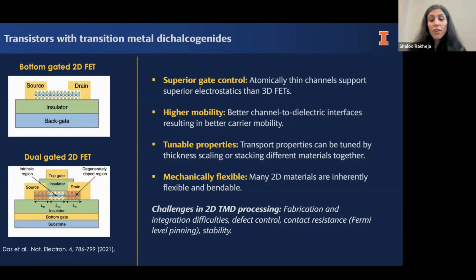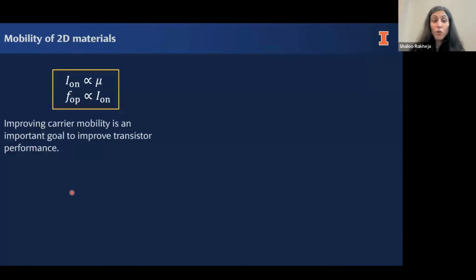And I should mention that there are lots of challenges in 2D materials related to, for example, how can we reproducibly synthesize these materials on a wafer scale, right? If we can't have a process that is wafer scale, we wouldn't be able to use it at the same cost as a silicon process. The second thing is, even though these materials are naturally passivated, they can have defects within the plane of the material. So how do we control those defects? And then, as I mentioned, contact resistance is a biggie for these materials, because if you can't optimize the contact resistance, you're not going to get a lot of current out of the device. And finally, some of these materials are not very stable in air. So those are some of the challenges that one has to address.